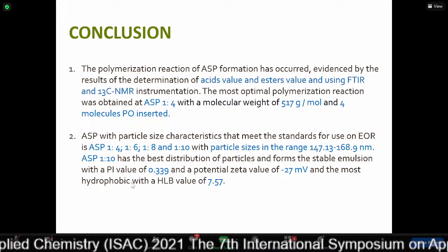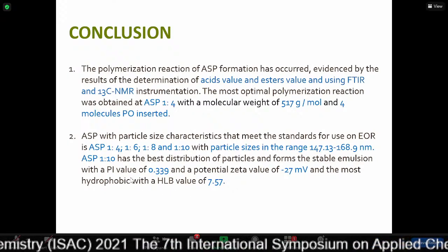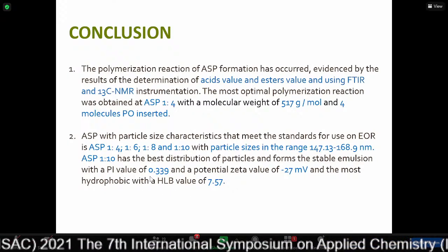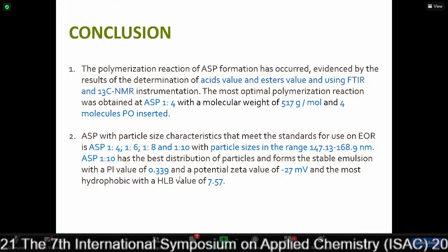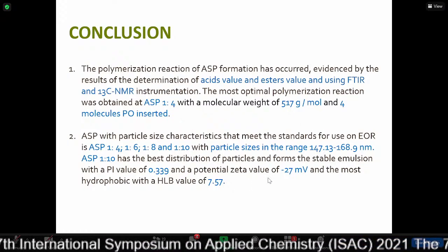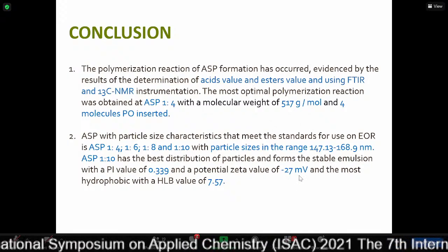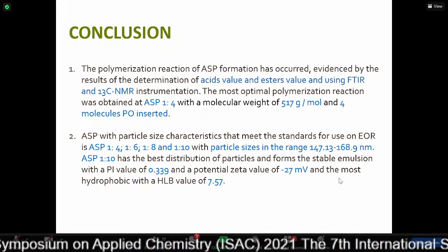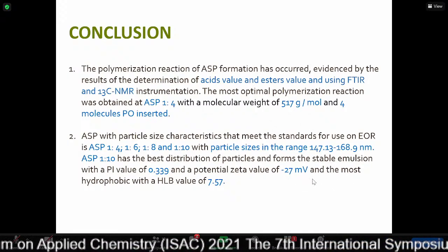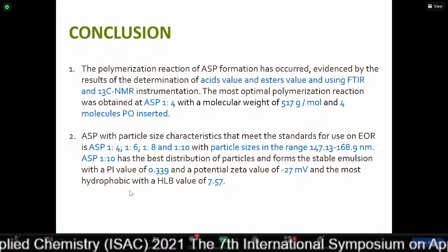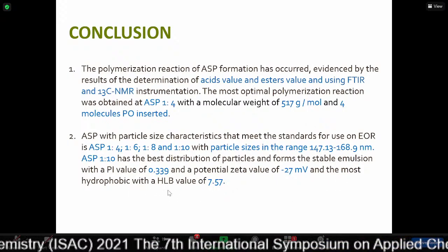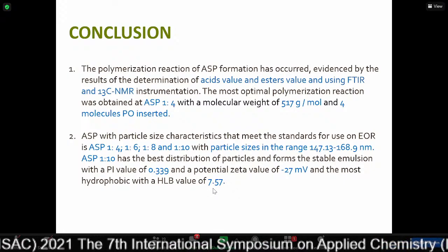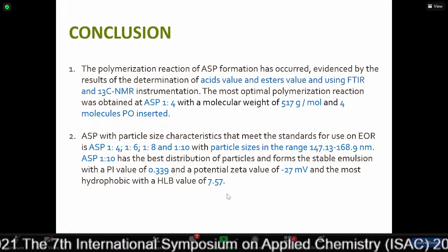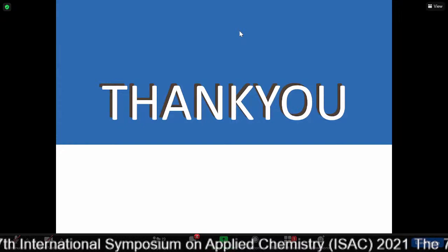When the stearic acid propoxylation ratio is 1:10, it has the best particle distribution and a stable emulsion, with a polydispersity index value of 0.339, a zeta potential value of minus 27 millivolt, and it is the most hydrophobic with an HLB value of 7.57. Thank you. I will stop the share.